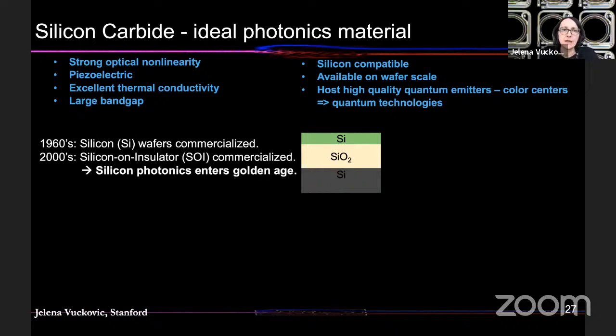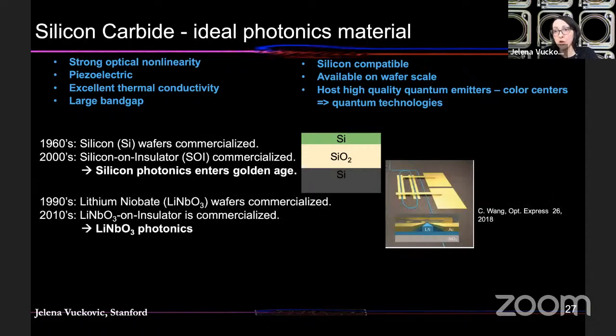It has excellent thermal conductivity, large band gap, it's piezoelectric, and it has strong optical nonlinearity, including second-order optical nonlinearity like lithium niobate. In fact, not very different from lithium niobate, a little bit smaller, but photonics is simpler to fabricate and process, so you have higher quality structures, which compensates for a little reduction in bulk nonlinearity.